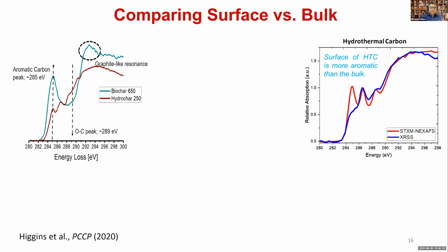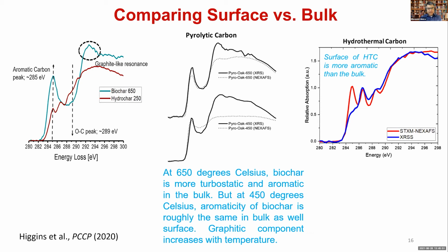We conducted both XRS and NEXAFS on hydrothermal carbon materials, which were lab created, and you see this huge difference in the aromatic peak of the same material using two different techniques. So it clearly shows us that the surface of the hydrothermal carbon is much more aromatic than the entire bulk, or the overall carbon budget, of these materials. Similarly, when we did these NEXAFS versus XRS studies on biochars at different temperatures, we also saw that at 650 degrees Celsius, biochar is much more turbostratic and aromatic in the bulk, while at 450 degrees Celsius the aromaticity of biochar is roughly the same in the bulk as the surface, but again, the graphitic component increases with temperature.